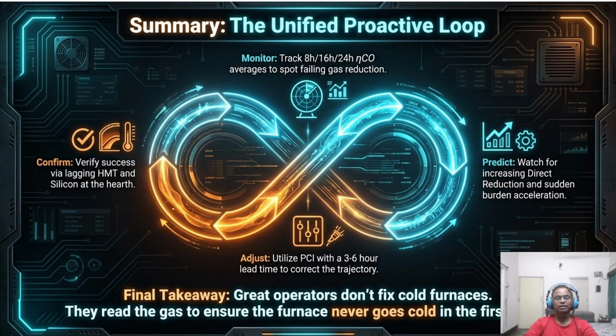We predict the chill by watching the increasing direct reduction. We adjust using PCI with that 3 to 6 hours lead time. And finally, we confirm our success by looking at the HMT, hot metal temperature, at the hearth.